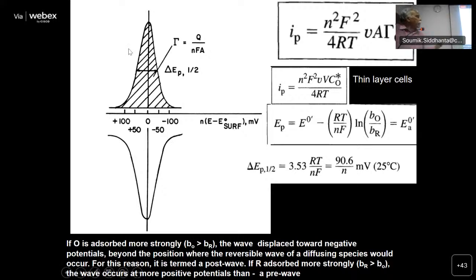The oxidation and reduction peaks happen at the same potential. The delta EP is 0. Remember, otherwise delta EP is 59 millivolt. So here you get 0, and that shows surface confined species, and their peak current is linearly related to scan rate. If you know the peak current and plot it against the scan rate, you can calculate this gamma star. Gamma star is nothing but surface coverage. Monolayer, multilayer, sometimes partial coverage, 0.1 monolayer. So the surface coverage can be quantitatively estimated if you get such voltammograms. So whenever you get such beautiful voltammograms where cathodic and anodic peaks happen at the same potential, don't throw them away. This is something very beautiful because you are able to measure the coverage, even if it is very small. So this is another interesting aspect of voltammetry.